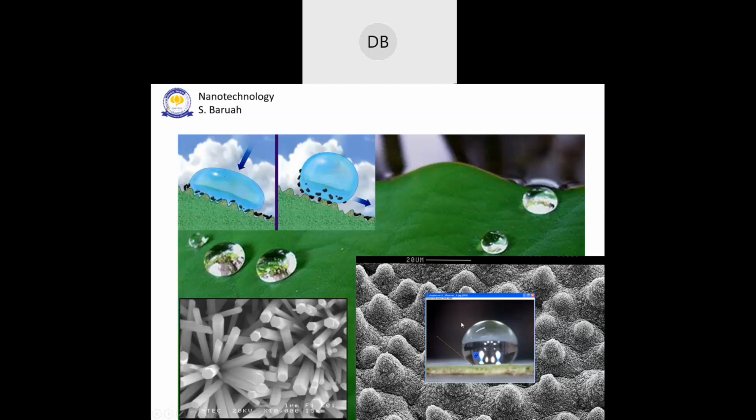And then using the same instrument that I designed, we took photographs of water droplets on surfaces like this. You see here, this is a surface that we developed with this type of rods on the surface, and you see the water droplet was close to 150 degrees, very similar to the lotus leaf. And just to make sure that these rods are playing the role, the base material that I used for this experiment was this bandage, a bandage that is used to pull in blood.